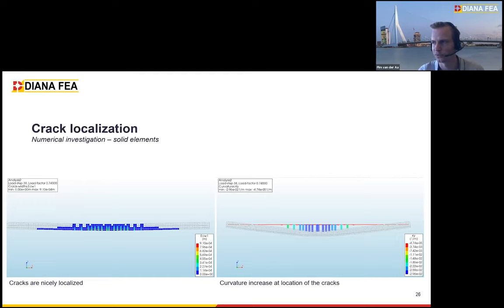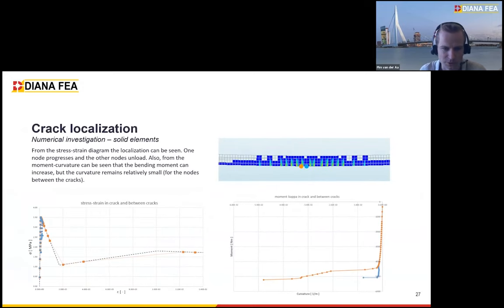So initially for the shell, we explained that there's only one moment curvature diagram. But for the solid elements, this doesn't apply anymore. That has to do with what we can also see here. If you look at two points, on the right side you have your moment curvature diagram. The orange line basically gives us the moment curvature relationship inside a crack. And the blue point gives us the relationship of the moment curvature diagram between cracks. What you can actually see is that it still remains relatively stiff. And that the bending moment can actually increase differently than you initially expected.